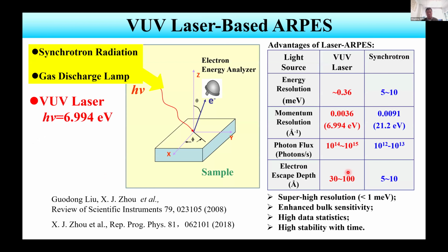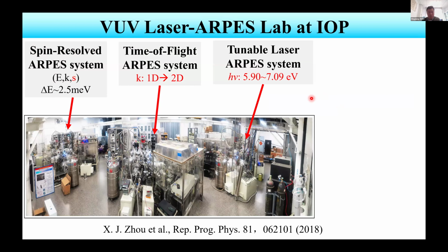In my group, we're using laser as the source for ARPES. I think the main advantage of using laser to do ARPES is that it can achieve a very high instrumental resolution. We can achieve about 1 meV in resolution. In the last more than 10 years, we have developed 3 systems. The first one is the laser ARPES. The second one is the spin-resolved ARPES. The third one is one where you can measure the 2D momentum at the same time.